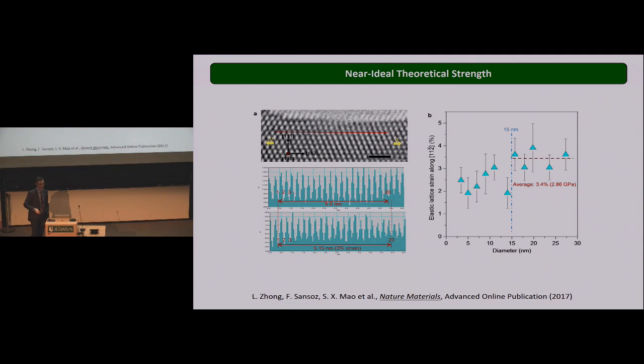And the last aspect I want to emphasize is that these materials, the silver nanowires, can be superplastic. What about their strength? So we measure directly from the lattice strain how much strain it takes to nucleate two dislocations. From that, we can estimate the elastic limit of the wires. And we find the elastic limit to be on the order of 3%, which, using the Young's modulus, represents about 2.8 gigapascal. And that is very close to the ideal strength for silver. All right, so not only can they be superplastic, but when they do this process, they are also near the ideal theoretical strength, which is kind of amazing.